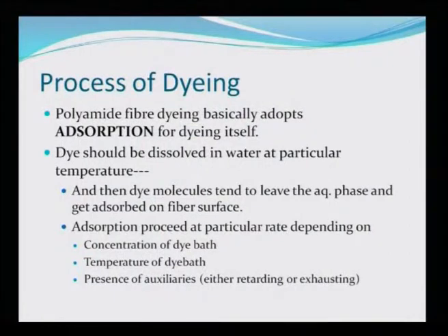The adsorption proceeds at a particular rate depending on the concentration of the dye bath, the temperature of the dye bath and the presence of auxiliaries, either retarding or exhausting agents. If you recall, similar retarding and exhausting agents were used in the case of polyester dyeing, which we learned a couple of lectures back. And there also the first step was the breaking of the dye aggregates, that is the solvation. The second step was adsorption, and here the dye adsorption is the first step, and then the dye migration and so on and so forth.